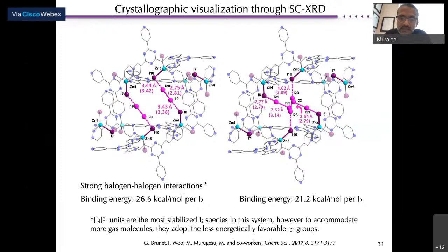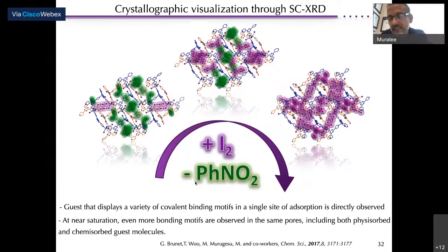And by doing a simple gravimetric method, we can see clearly that this ArMOF is one of the highest absorbing iodine systems out there. And we can see how dynamically it's absorbing, in terms of the I2 molecules replacing some of the nitrobenzene, and you can visualize this crystallographically. Physisorbed and chemisorbed iodine are seen within the framework, and it can take a really large amount of iodine. What this teaches us is that if we want to do iodine capture, it is ideal to create a system that has an iodine as an anchor within the framework, and this iodine clips on it and enables further capture.